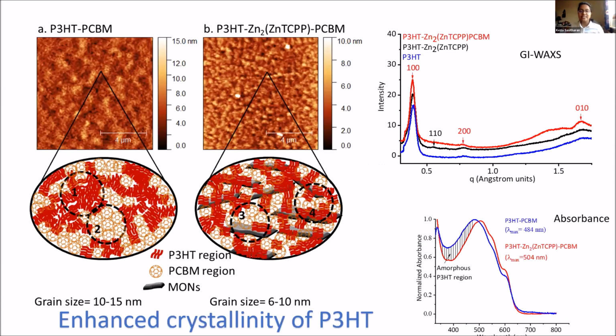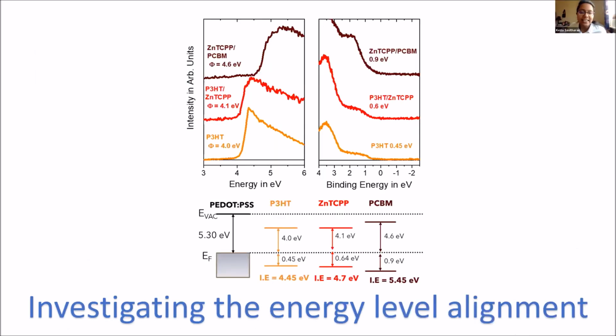We did further analysis and came to the conclusion that MONs act as templates for improved crystallinity of the polymer, which is supported by the calculation of grain sizes from AFM investigation and also from the GIWAXS data and the absorption spectra, where we observe a decrease in the amorphous P3HT region. Currently we're investigating the energy level alignment of these systems in the ternary blend to see what role the energy levels play in contributing to an enhanced performance without creating traps for the excitons.